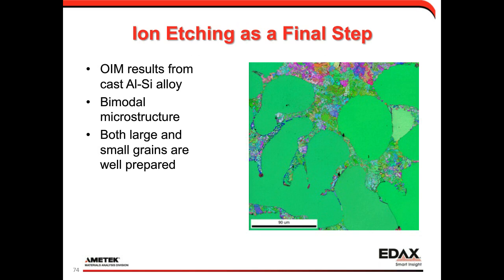This is an example from a cast aluminum silicon alloy where ion etching, broad beam ion etching, is just used as a nice final step to improve the quality. So this is one that we prepared with our mechanical recipe, and then the ion beam preparation was used as a final polish to just improve the final results. And so this is a dual phase sample. It just helps clean up the final results very nicely. This is using the Fischione SEM Mill.